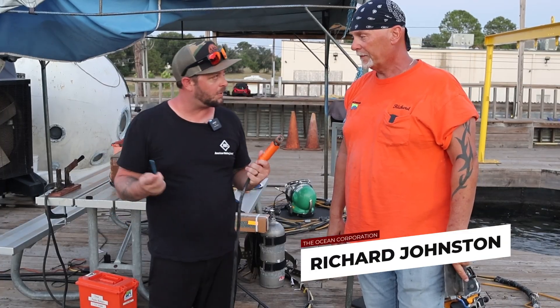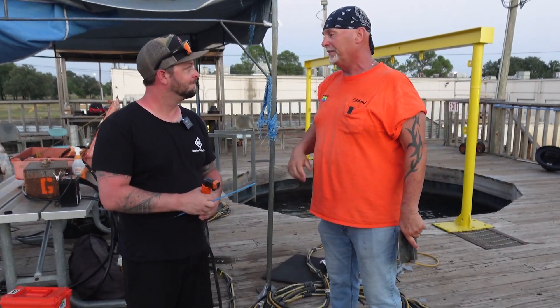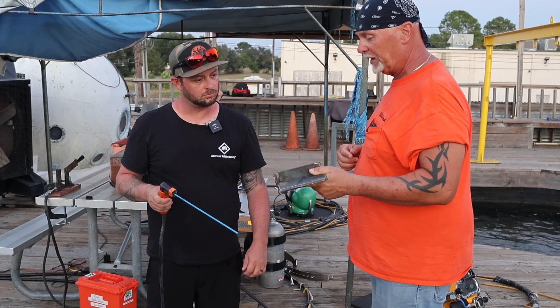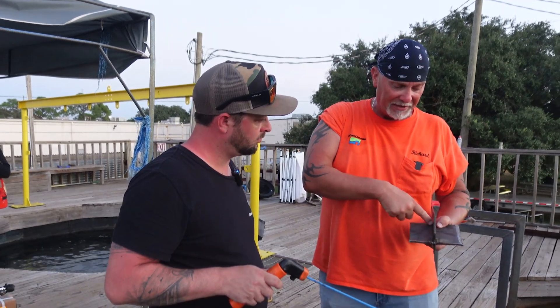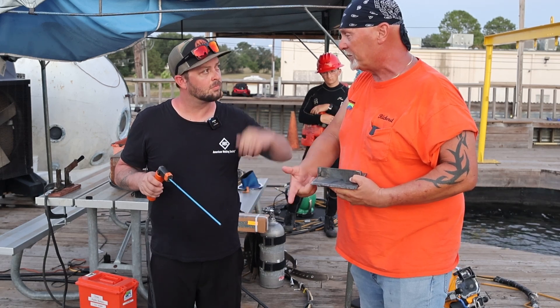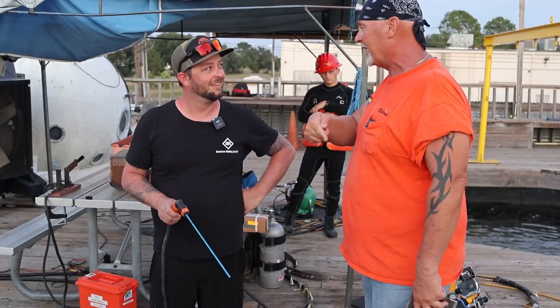So explain to me the process of what I'm about to do here. Everything you learned on how to be a welder and how to stick weld — forget it. We got our insulated stinger rod holder. You're going to be welding fillet welds: 1F, 2F, 3F. Your trick is the rod has to maintain contact with the metal the whole time — it cools the puddle real fast and you got bubbles coming up. Turn off your welder brain, turn on your lazy diver brain. Let the rod do the work. Start about a quarter inch from the end, push and twist once it arcs, lean, push it back, and just slow drag all the way across until it drops off. Slow bead all the way across.